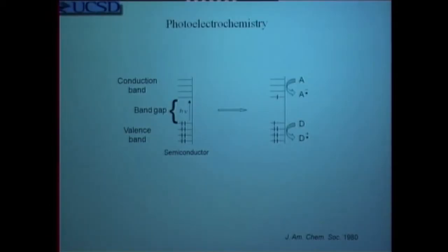This led us to think very deeply about the way in which electrochemistry and photochemistry can be combined into what we call photoelectrochemistry. Like the systems that I've showed already, there is a gap between filled and vacant orbitals in something like titanium dioxide. If we supply a photon that has enough energy to be equivalent to the band gap, you can promote an electron from the filled orbital to the empty orbital and can trap that extra electron by having an acceptor which is bound to the surface pull that electron out and be equivalent to a reduction.